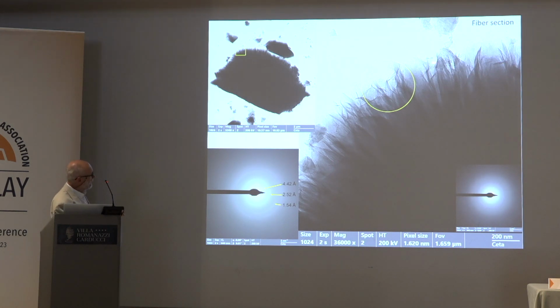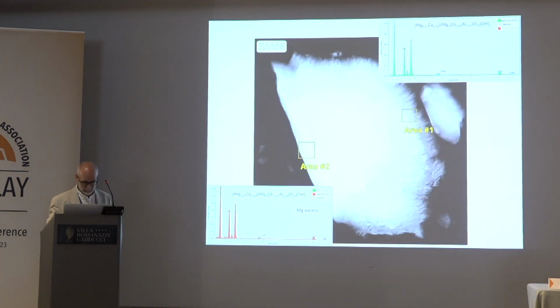But the flakes, in some of them we get the electron diffraction pattern, and the electron diffraction pattern is compatible with saponitic clays. In scanning TEM, you obtain the picture and analysis in the flakes and the core. Analysis, then we recalculate as a structural formula, and for the layers, this part is close to saponite.